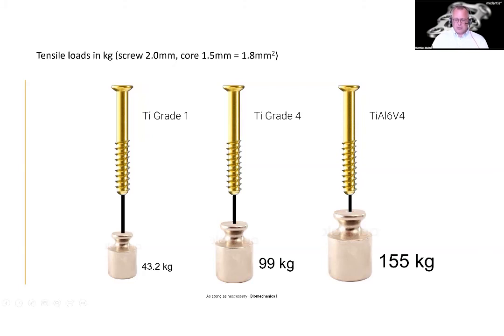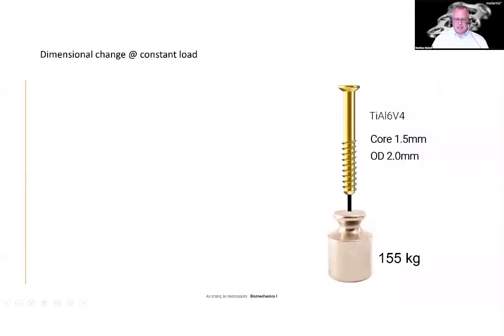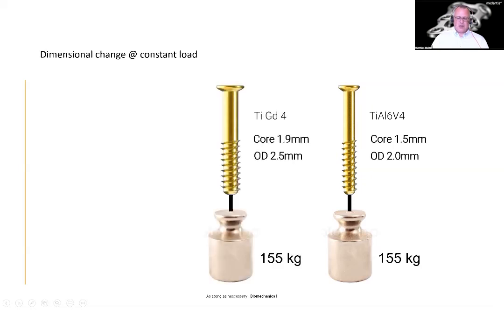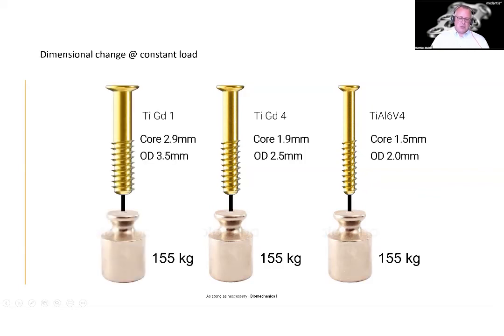And if we take this 155 kilos as our standard, a constant load with a dimensional change, then a 2.0 millimeter screw of titanium aluminium vanadium can lift 155. If it would be made of titanium grade 4, it would already have an OD of 2.5 millimeter, half a millimeter more. And if it would be made of titanium grade 1, no one would do this, it would already be a 3.5 millimeter screw. So that tells you the influence of why choosing the right titanium grade is ever so important.